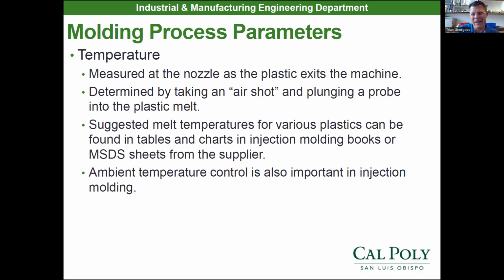So I got kind of mixed up there. The melting temperature of the material, we looked that up. It's right around 590, 585 degrees. We're going to set the nozzle temperature there, but not the barrel temperature. We set the barrel temperature about 10 degrees below the melting temperature of the material. Then we melt it right at the nozzle.